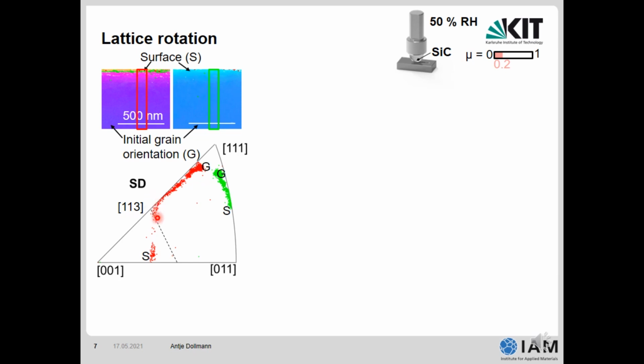And then something unexpected happened. So here close to this 113 direction, the orientation leaves the bisector. And one reason could be that the stacking fault behavior changes along this dashed line. In uniaxial tensile tests, the stacking fault width increases here in this part and decreases here in this part. And under compression, it's vice versa.